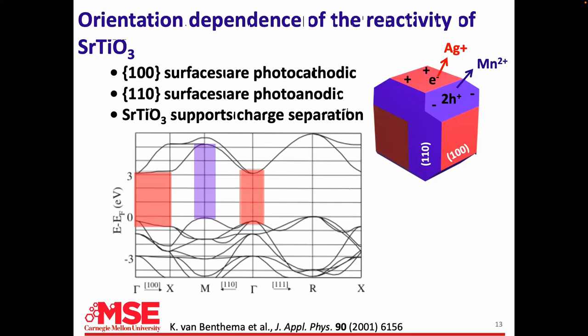What about the anodic surfaces? Those are at the end point in the zone and I don't have enough light to excite those holes. What must happen is that the holes being excited here — the height of the valence band here is greater than all other points — so holes should collect there if they can migrate. It's a hand-waving argument; it'd be nice for theorists to work this out. But it seems the holes migrate to these surfaces because that's the highest point of the valence band.